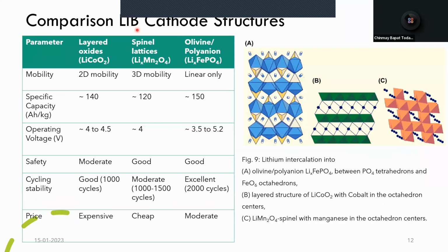When we take a look at the lithium-ion battery cathodes, we primarily have three kinds of structures, as we see in this graphic. That is layered oxides, spinel lattices, and olivine or polyanion oxides. Layered oxides offer two-dimensional mobility of the lithium ions. Spinel lattices offer three-dimensional mobility, and olivine or polyanion oxides offer only linear mobility. Layered oxides are typically known as nickel, cobalt, manganese or NCM cathodes, and they are very popular due to their high theoretical and practical capacities, and they make an ideal counter electrode for graphite. The largest drawback, however, is their safety and cost due to the use of cobalt.